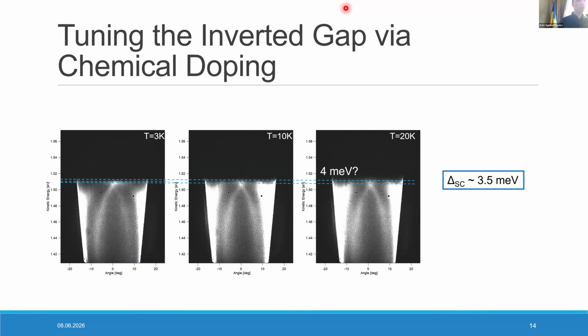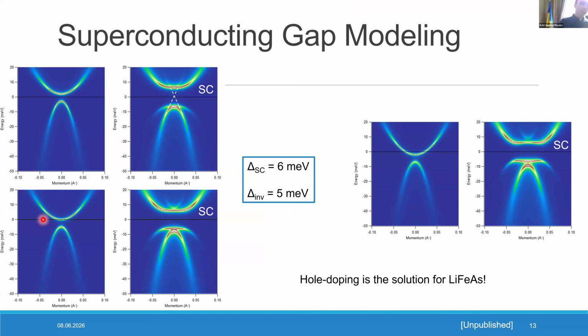And this is what we have done. We've measured lithium iron arsenide doped with 1% vanadium. First of all, 1% vanadium doping decreases the superconducting temperature. Now it's not 18 Kelvin, it's around 10 to 11 Kelvin, and therefore the superconducting gap naturally also decreases. Both from our measurements and because it changes linearly in this case, it corresponds nicely that the size of the superconducting gap is about 3.5 meV. At the same time, the Dirac point position, from careful data analysis, is around 4 meV, but there can be a bit more done with it. This brings us closer, unfortunately, to the second case, which still is better than what we had before.